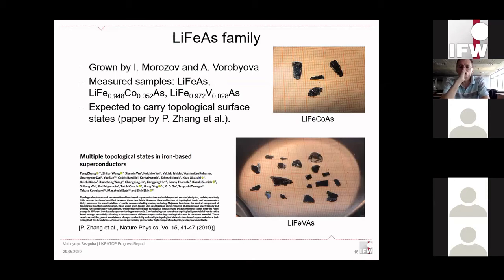It was grown by Igor Morozov and Anna Vorobyova, and we managed to measure not only pure LiFeAs, but also doped with cobalt and with vanadium, which in this case serve as electron doping and hole doping, essentially. And these materials are also expected to carry topological surface states. There are articles by the same group where they report seeing topological surface states and Dirac cones.